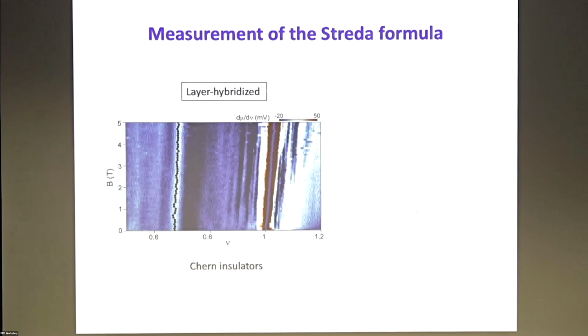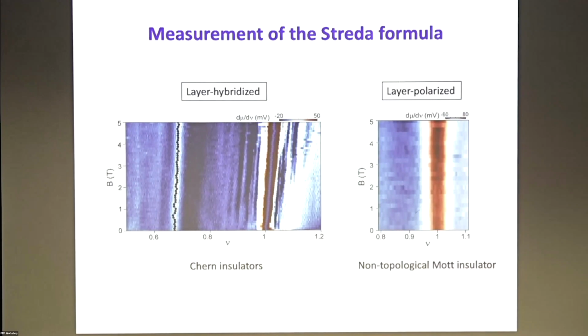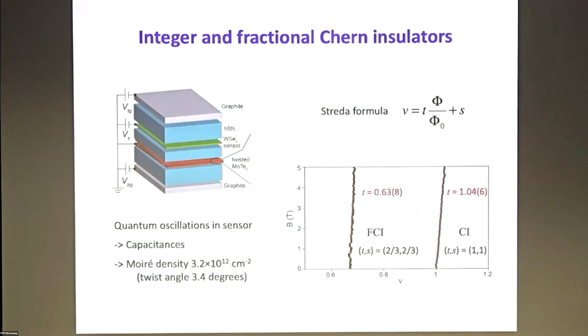And this is the measurement. I'm plotting again the incompressibility, in this case versus filling factor and magnetic field, not the electric field. We fix the electric field at 0 so that the bands are topological there. So this is the layer hybridized region. And now you can actually see that the -1 and the -2/3 states both disperse under a magnetic field. So that measurement shows that indeed they are Chern insulators. And as a control experiment, you can apply a large electric field, where the -1 state still survives. You can look at its dispersion under a magnetic field, and there's no dispersion once you layer polarize the bands. And this is just a Mott insulator that does not have any non-trivial topology.